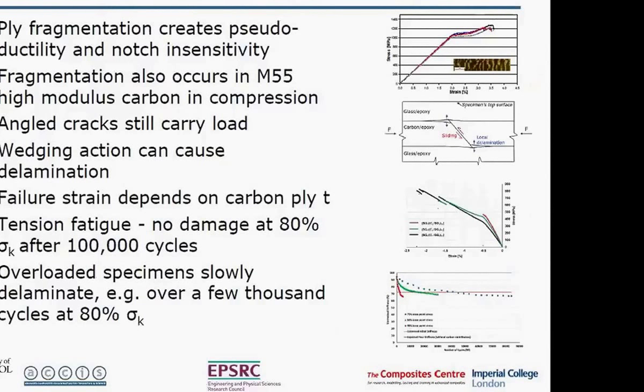In tension fatigue, we see no damage in the pristine material at 80% of the knee point stress after 100,000 cycles. If we pre-load the specimens to overload them first, so we've got some damage, then we do see some delamination, but it's relatively slowly occurring over a few thousand cycles at 80% of the knee point stress.